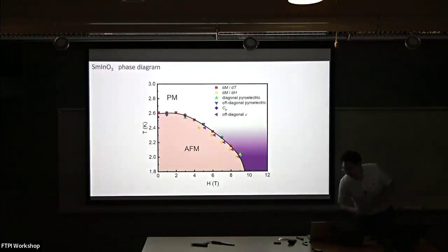And the second reason is this sample has a significant off-diagonal magnetoelectric response. So when you have a polarization and a magnetization perpendicular to each other, the spin wave along the third direction is allowed to have a non-reciprocal feature allowed by symmetry, which means the spin wave might be asymmetric under the plus K and minus K transformation.